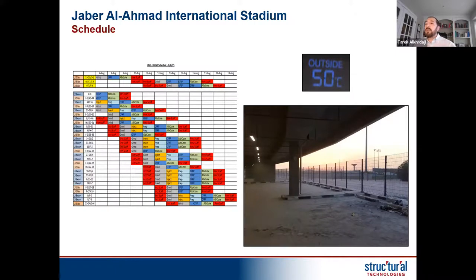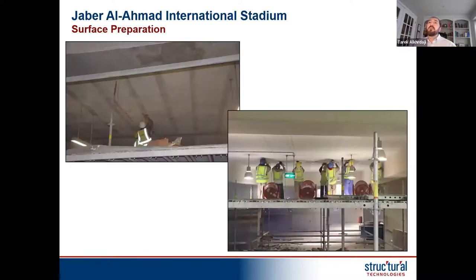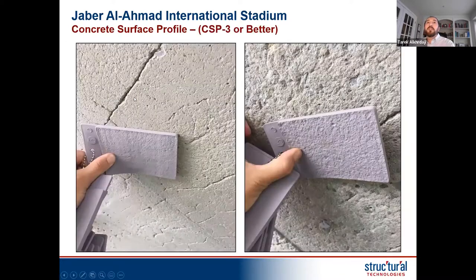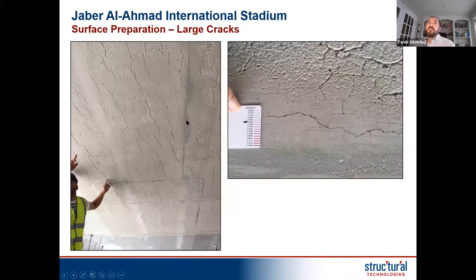But in some areas, for example, the US South, Arizona, Florida, Texas, this sometimes becomes a concern that we have to address. Here you can see all the marking and grinding of the concrete surface. You can see the roughening of the surface. This is surface profile 3. This is 5. This is just to show that in some areas workers weren't too aggressive, so they're told, no, you can back off, you don't need to go that aggressive. And these chips from the International Concrete Repair Institute really provide a good guide for verifying the surface.